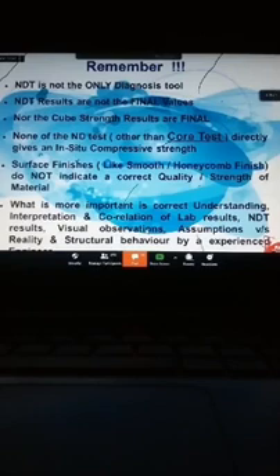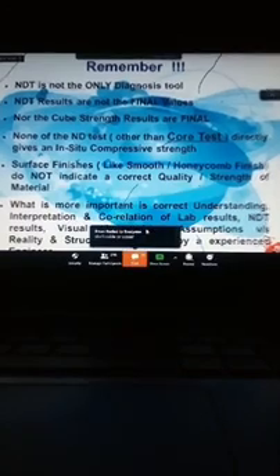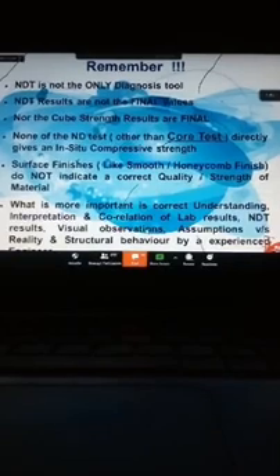If you have, suppose, M20 concrete, and the cube is crushed at say 25, then I see that most of the time, 90% of the time, people accept that cube. That cube concrete is declared as accepted simply because it has crossed a figure of 20. So there are many issues even with the acceptance of the cube.